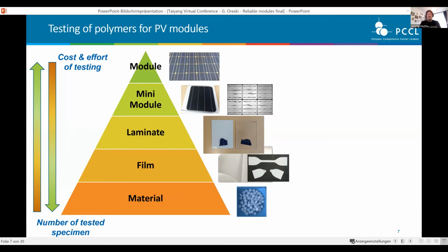And as the pyramid shape, you know, at the base of the pyramid, you actually test a large number of specimens, and you go to the next level just with the most promising materials. And in the end, you make just some module tests with the most promising candidates that have not been eliminated in each step. The thing is, the higher you go up in the pyramid, the higher is actually the cost and effort of testing. So in the past, unfortunately, shortcuts have been taken. I will show a very bad example of this. Therefore, we say, let's say, unexpected PV module failure modes occurred after some years of deployment in the field.